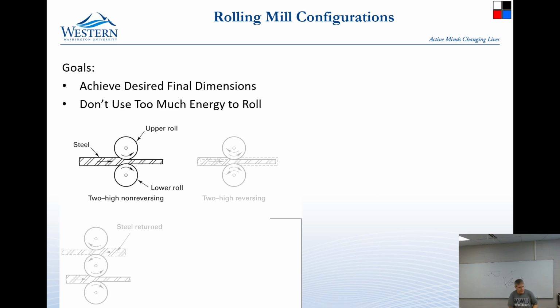So one way to roll things is to run them through a set of rollers and then run it back through the same set of rollers. You move them a little closer together, then you move them a little closer together, and you roll it back through. That works when you're doing the powering, but on an industrial process, that doesn't work very well because these giant rollers, you have to slow them down and stop them and then reverse the direction so that they can go the other way. And that's a huge amount of wasted energy. So instead, what they do a lot of times is they do a 3-high nonreversing. So now you can put the material through the bottom, and then you lift it up, you run it back through the top, and those rollers can just keep turning the same direction all the time.